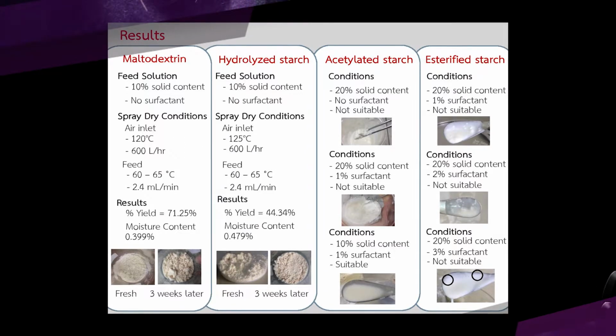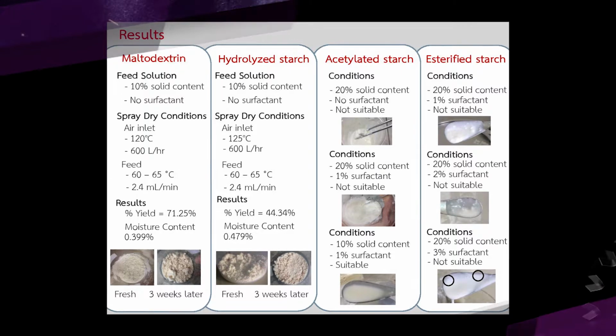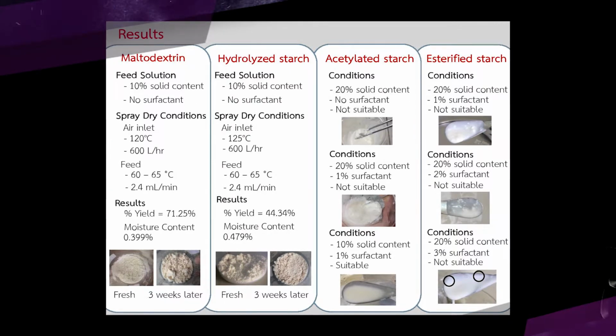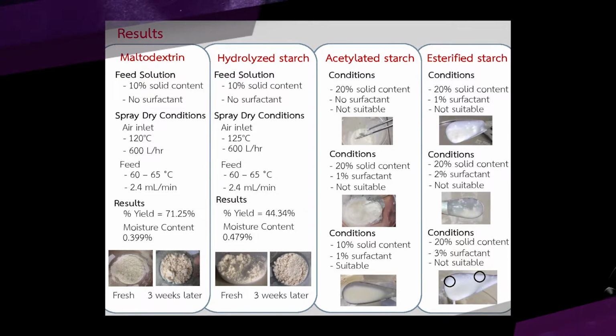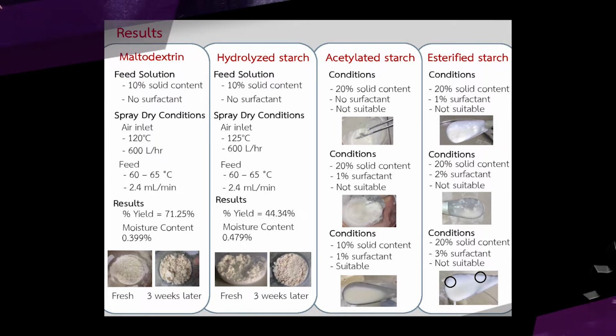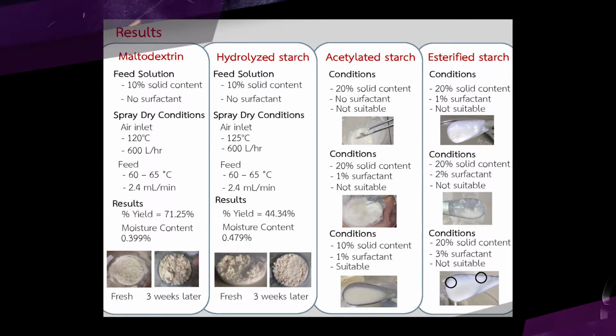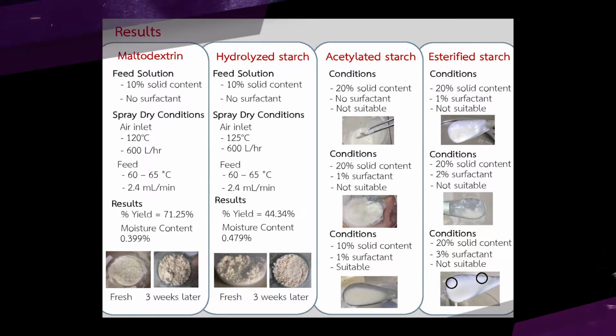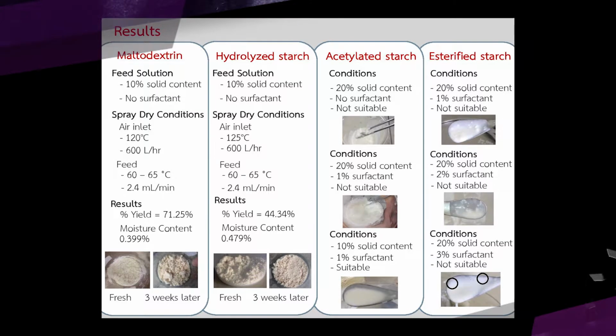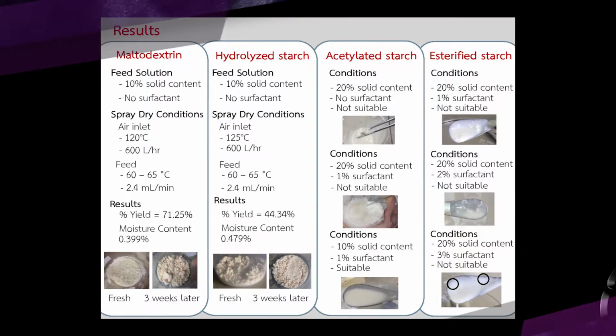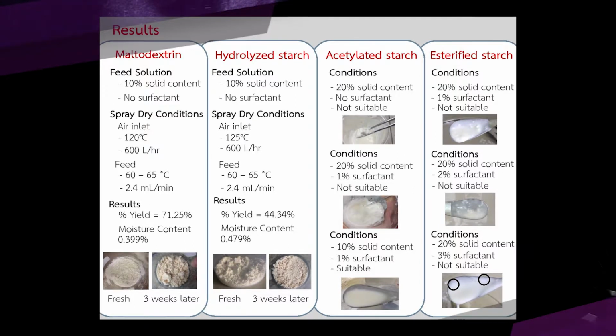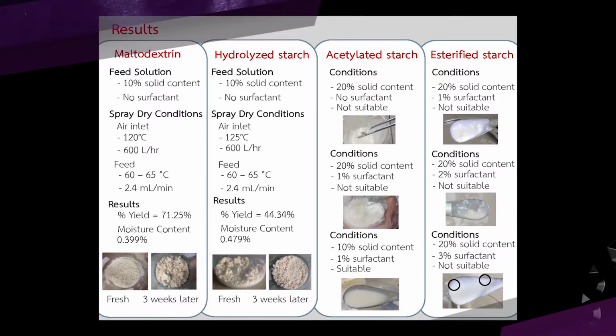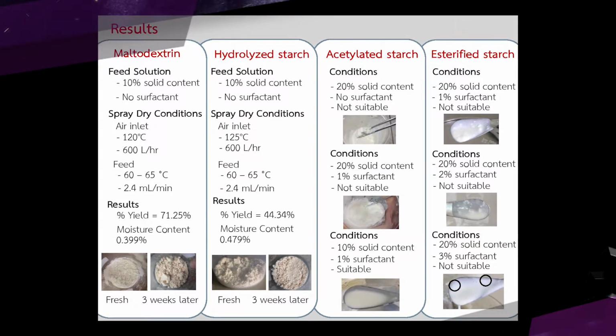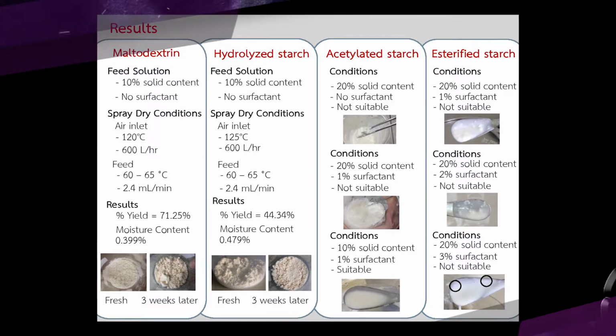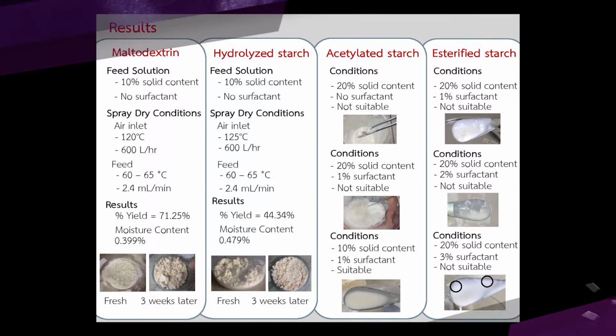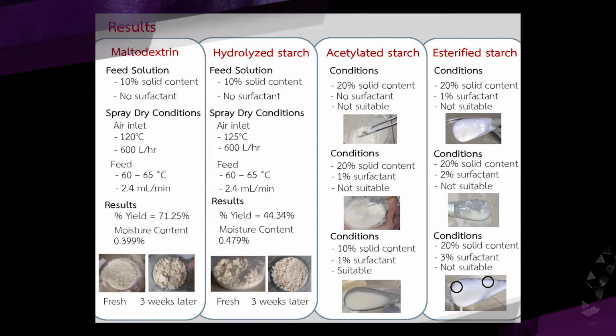For hydrolyzed starch, we use the same feed solution as maltodextrin, but for the spray dry condition we change the air inlet temperature to 125 degrees Celsius. The result that we get is lower percent yield with higher moisture content. We left it for 3 weeks and it turned yellow with small coagulate, but there was more compared to maltodextrin. For acetylated starch, we use a 20% solid content with no surfactant. However, it's still in heterogeneous form, so we decided to add surfactant, and it became a viscous liquid, so we decrease the percent solid content down to 10%.